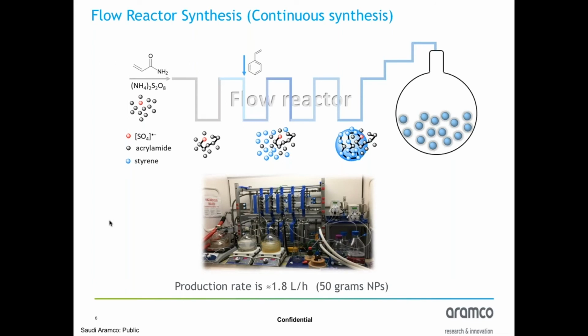The size of the as-made nanoparticles is narrowly distributed in the range of 20 to 60 nanometers in stable colloids that have a shelf life greater than 1 year at ambient conditions. The innovative nanotags are designed to be compatible with the water-based drilling fluid via addition of hydrophilic comonomers or ionic surfactant. This compatibility can be further adjusted via the reverse emulsion for use in oil-based drilling fluid as well. Worthy to mention that the hybrid nanotag synthesis process uses very safe microreactors, and the whole process was optimized for safe operation.